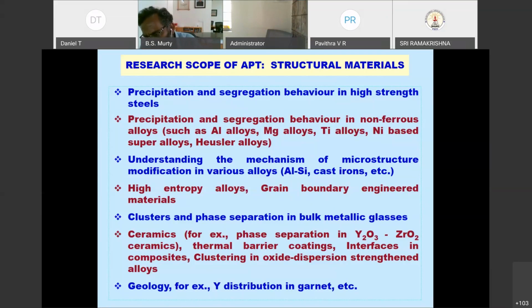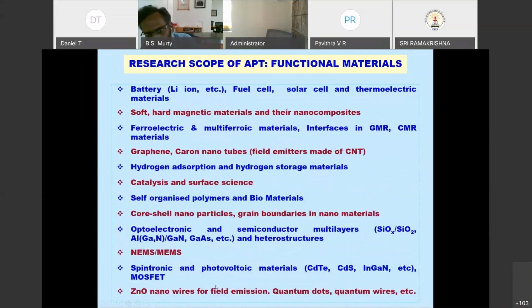Because please also remember, in the atom probe, in order to ensure the atoms do not move from their original positions, we cool the sample to about 40 Kelvin. So the chamber that you use in the atom probe, the sample tip is always cooled to about 40 Kelvin. At that 40 Kelvin, we freeze all the atoms so that we will be able to know exactly which atom is sitting where. So you can have a variety of materials, including some oxide materials, which can be seen without any difficulty. And a variety of functional materials: batteries, ferroelectric materials, multiferroic materials, you name it, magnetic materials, carbon nanotubes, and in catalysis, for example, core shell nanoparticles people are preparing. So the only thing you need to do is, can I prepare a sharp tip out of a sample? If you have a sharp tip out of any sample, in principle, any sample can be converted.